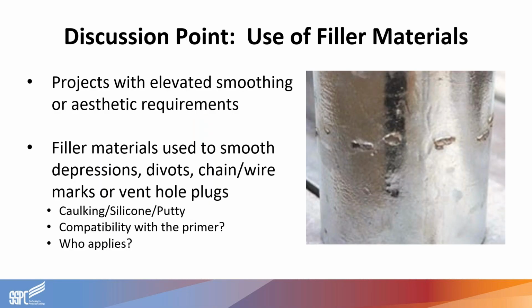So we talked about the roughness or high spots, but it also may be desired to fill in low spots or depressions to even out divots or indentations in the galvanized coating to further achieve that smooth surface. We also see this when looking to paint over vent and drain hole plugs, which have been pushed in to fill in vent and drain holes.